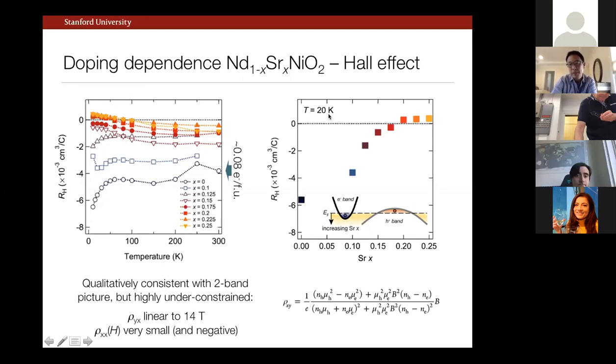So similarly to the resistivity here, if we look at a low temperature normal state slice of the Hall coefficient, we can see that there is this zero crossing. And again, it's suggestively close to, in the immediate vicinity of, the superconducting dome. So these 4 samples here are those that are superconducting.